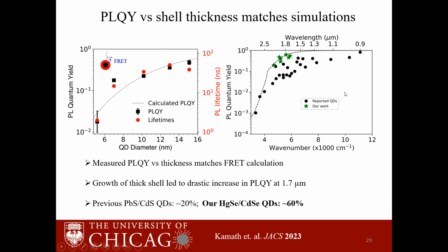But the fact that we see an agreement of our theoretical trend with the data tells us that 60% is not just the end. And if we have a way to grow a thicker shell, this could, in principle, reach 100%.